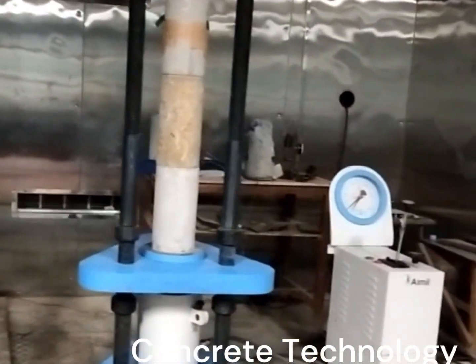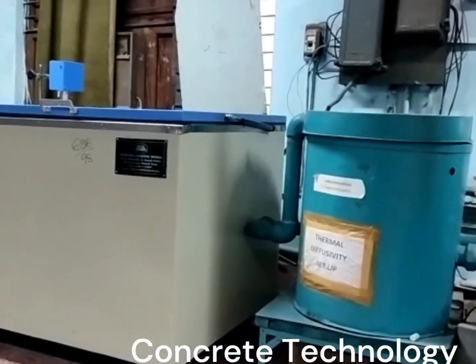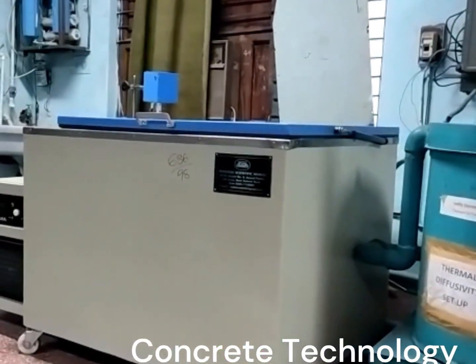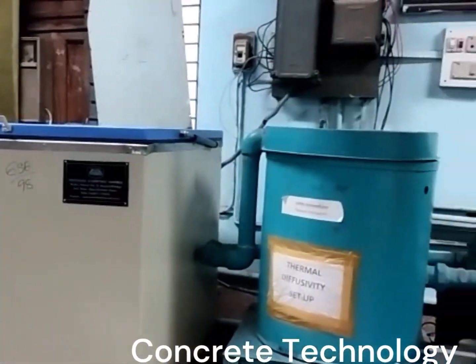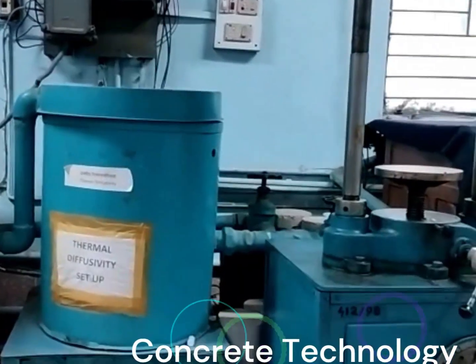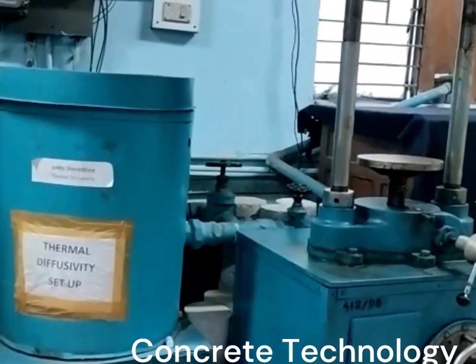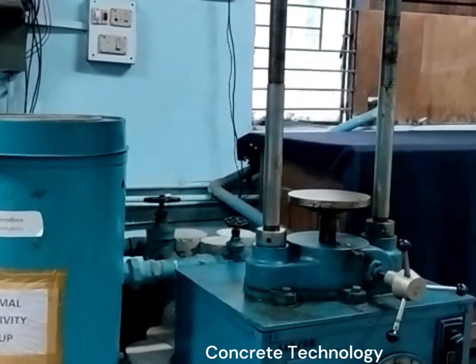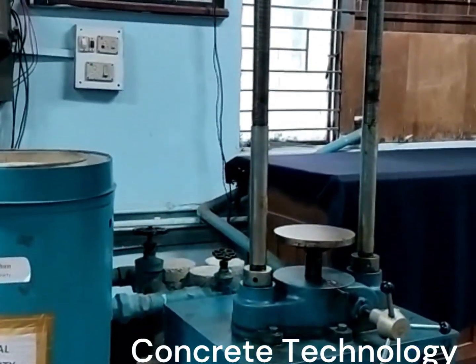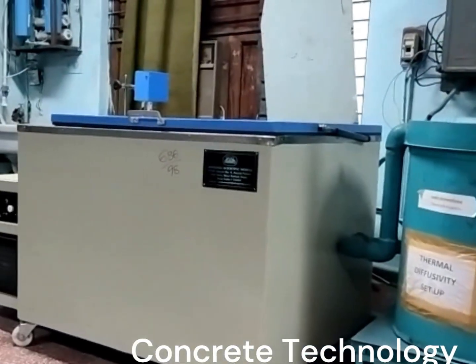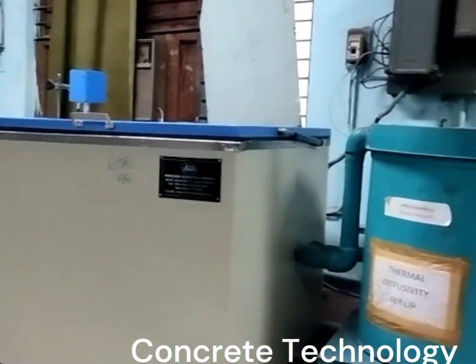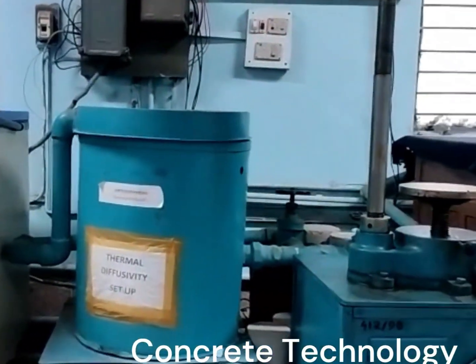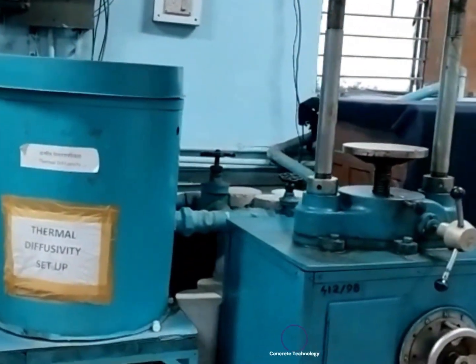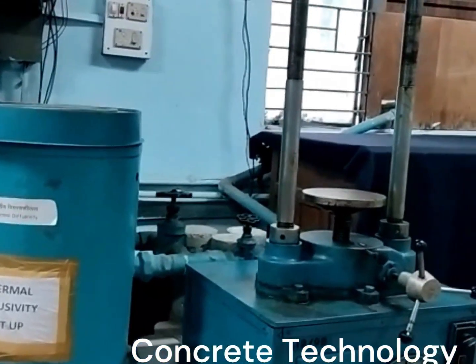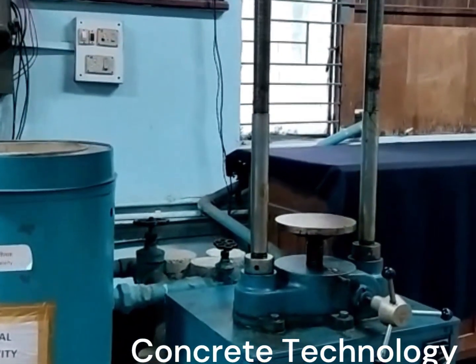5. Constant temperature water bath. The constant temperature water bath is required to evaluate the coefficient of thermal expansion of mass concrete samples of 300 mm dia x 600 mm height cylindrical specimens. It is one of the important thermal parameters required to calculate the thermal stress, which is further used in determining the placement temperature, lift height and lift interval for placing mass concrete in gravity and RCC dams.